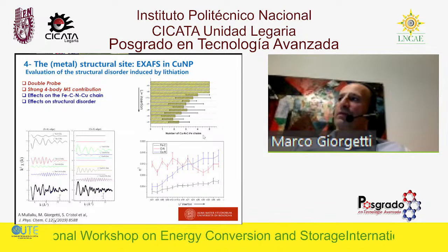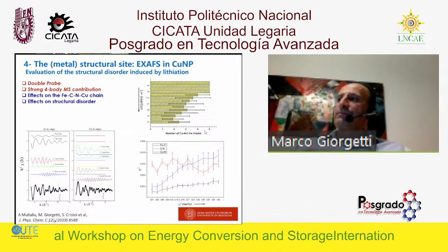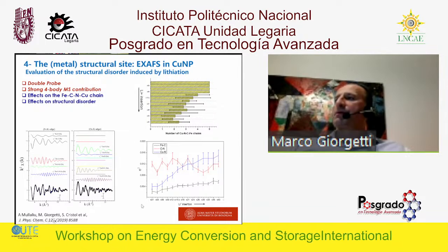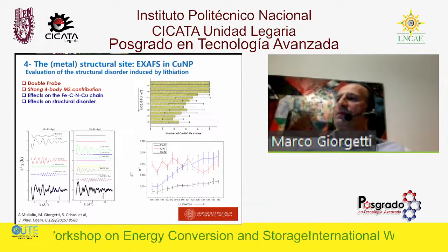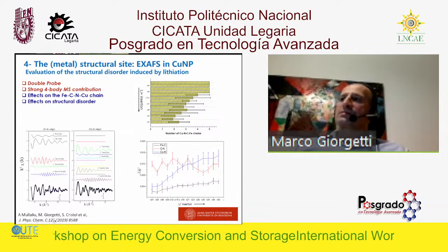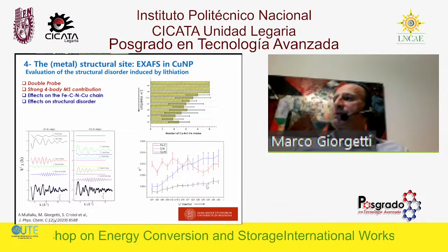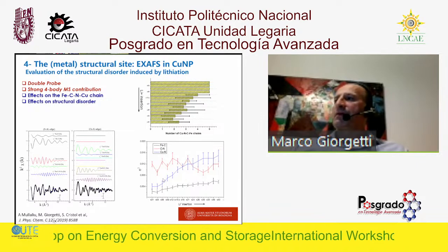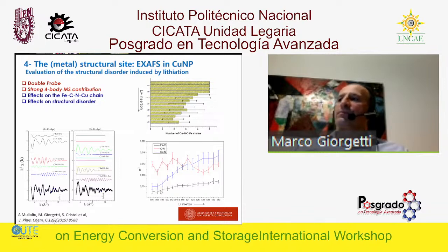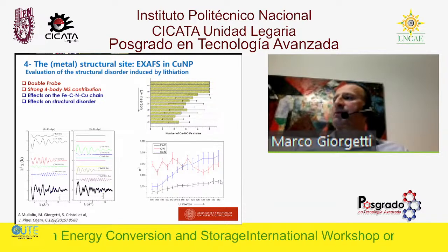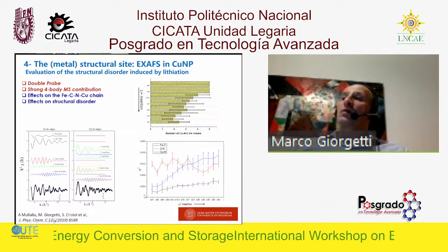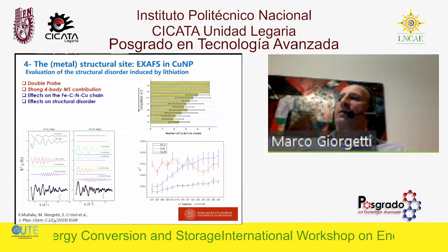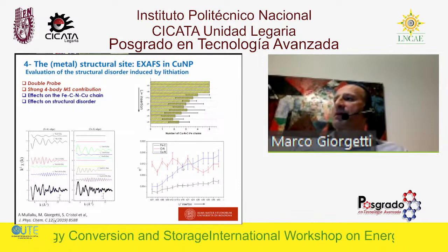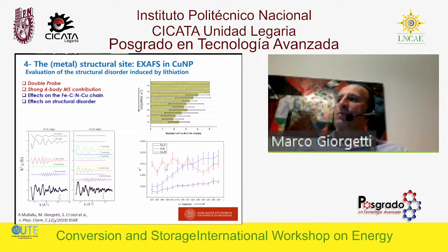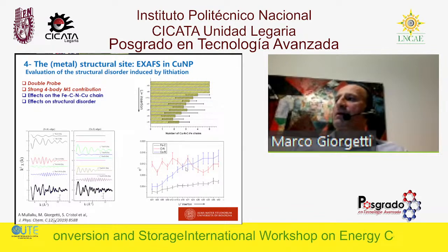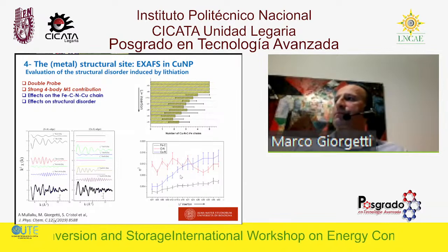But if you plot, during the lithium insertion, the behavior of those EXAFS Debye-Waller factors, we see that, for instance, the iron-C bond is okay, makes some disorder, but not that much. What is very increased in disorder is the copper-nitrogen bond. You can see from this graph that during lithiation, the copper-nitrogen bond has a strong variation in the structural disorder.